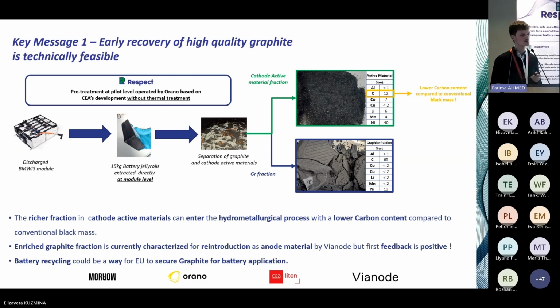Orano has performed on its site a first process step developed in the project to extract, without crushing and without thermal treatment, the electrodes contained in the module. So we managed to get access to around 15 kilos of this electrode. And then a second step was applied to start a first separation of graphite and cathode active materials, also performed by Orano. 2 main fractions are the output of this process.